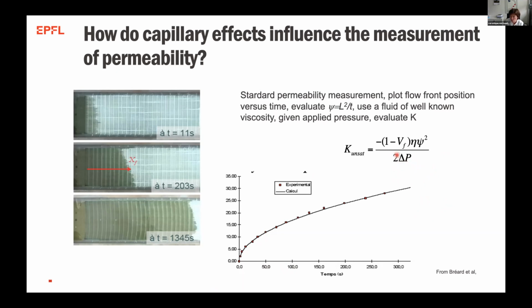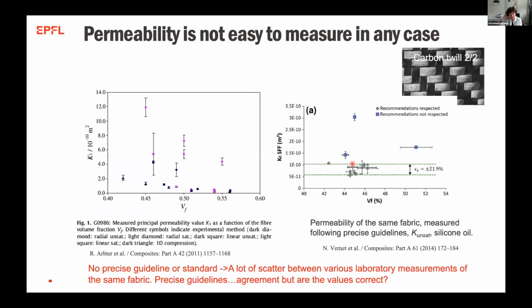Now, of course, you don't know what delta P is, so you say, well, delta P is the pressure that I had in the air minus the pressure that I applied. So I know delta P, and I find K, which we would normally call K unsat. Doesn't mean that the flow is not saturated, but it means that it's a dynamic measurement. I would call it K flow front, or K dynamic. But anyway, everybody calls it K unsat. Just to tell you in any case, permeability is not easy to measure.